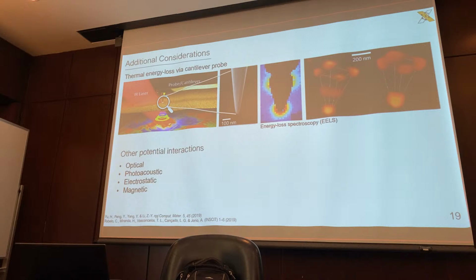In that case, I know that we have a very limited selection of materials that we can use in terms of coatings for our silicon probes, and gold has become the dominant coating for maximizing the plasmonic effect. So we'll have to find other ways of maximizing that at this point, unless we find new materials that induce that plasmonic effect better than gold. Because there are certain materials that you can't use, like silver. I think the plasmonic effect is not just coupled with material, it's also coupled with the shape and dimension of the tip.